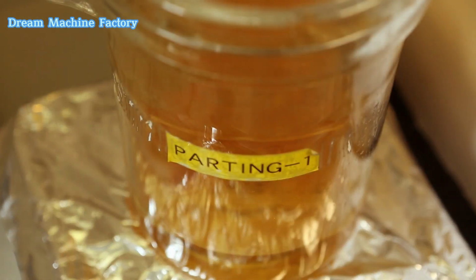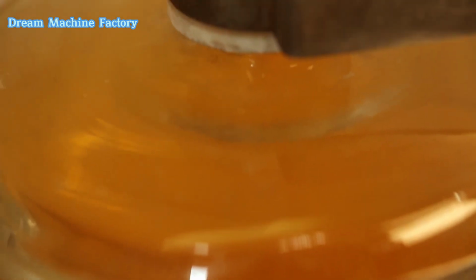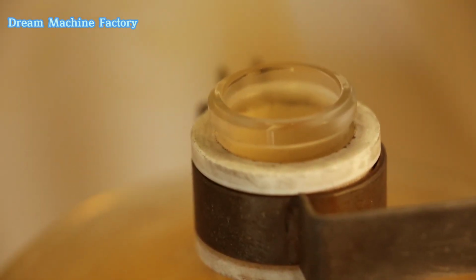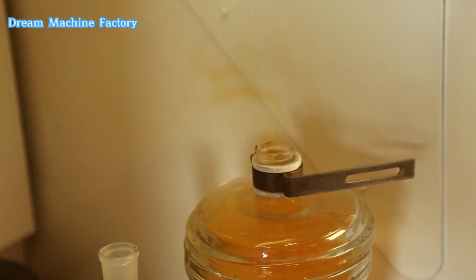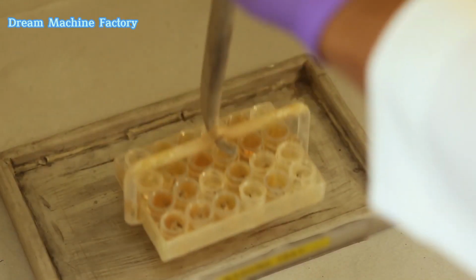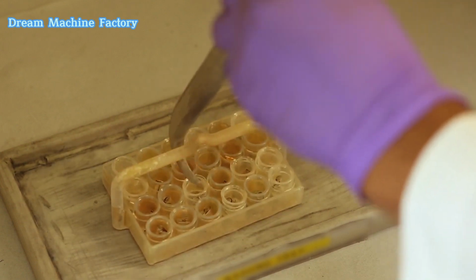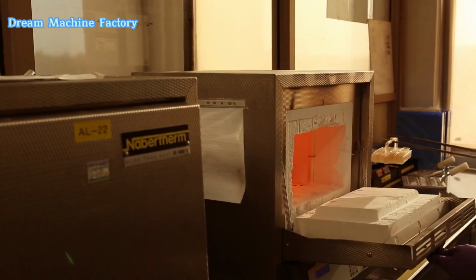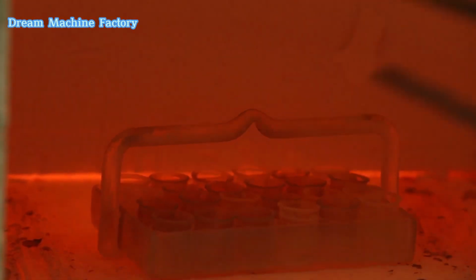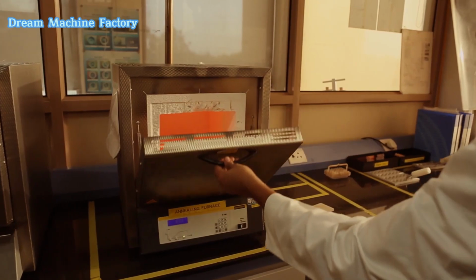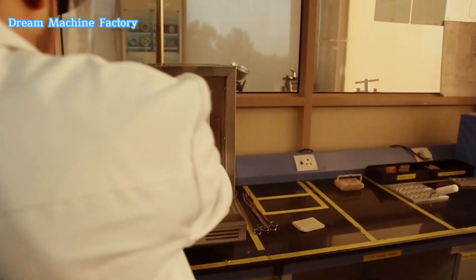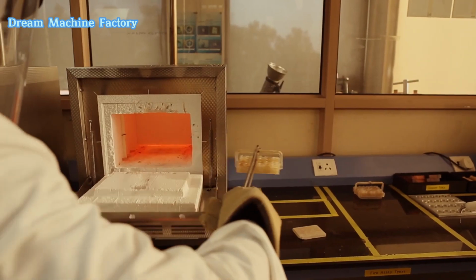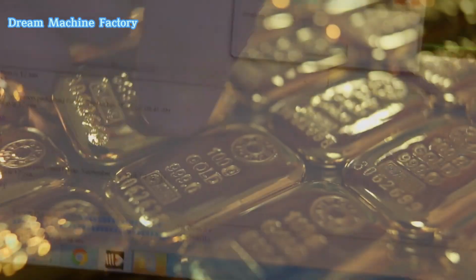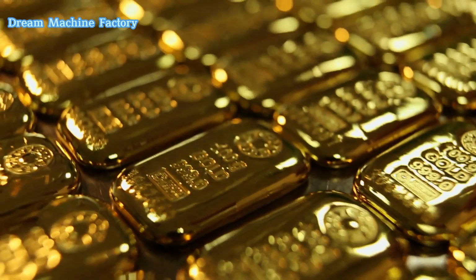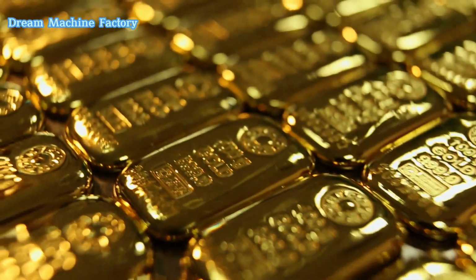In addition to fire assay, spectrometry methods such as spark spectrometry and ICP, inductively coupled plasma spectrometry, are also used to determine gold purity. Spark spectrometry uses a high-energy spark generated by ionized argon gas, which causes the sample to emit light. This light is analyzed to determine the elemental composition of the gold. On the other hand, ICP spectrometry creates a high-energy plasma from argon gas, enabling emission spectroscopy, a method that can measure gold purity with exceptional precision, even down to parts per billion.